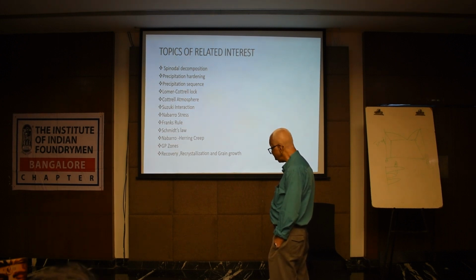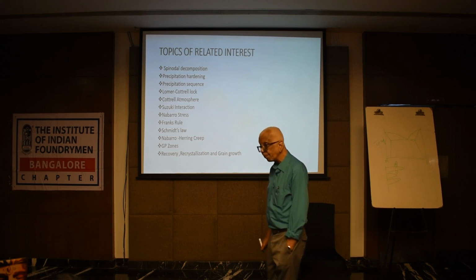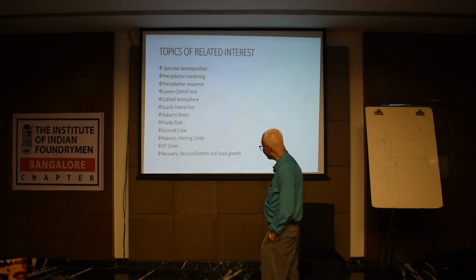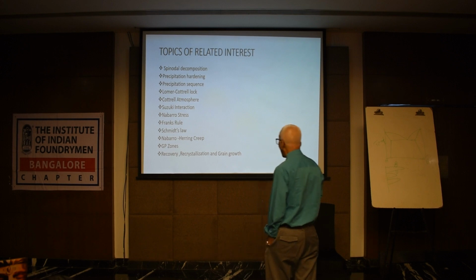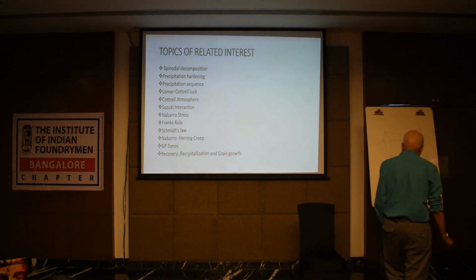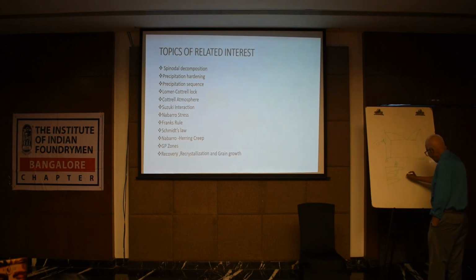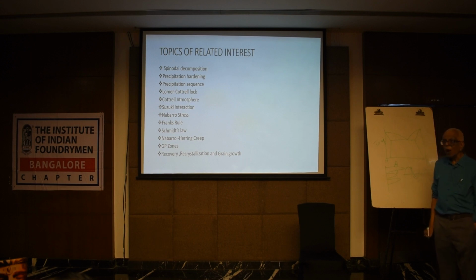Spinodal decomposition is actually like a perturbation. What happens is the concentration fluctuation will increase with time. In spinodal decomposition, there is a sinusoidal fluctuation and there is an uphill diffusion. In fact, I wrote a classic paper on small angle scattering of GP zones in aluminum copper alloy 2219, not aluminum copper magnesium, which my friend in Bangalore, Dr. Yeshwanthpur, gave the samples to me.